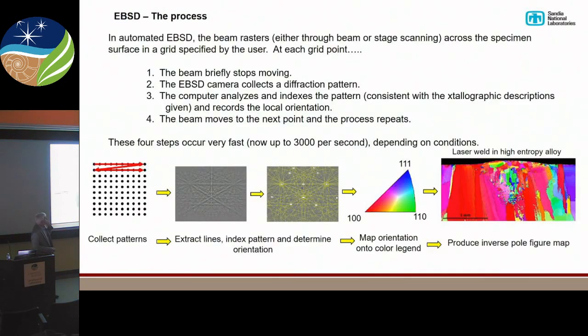So how do we actually do this? Commercial systems now do this quite well. I built my first system in 1992. It wasn't very fast at all, but it worked. So now we can buy a system where we scan the sample pixel by pixel, and you can pick the spacing of your pixels, how far apart they are. It depends on the microstructure you're trying to measure. We collect a diffraction pattern at every point. The system automatically finds where those lines are and the intersection of those lines, and then it compares that to a list of possible phase matches that we have listed.